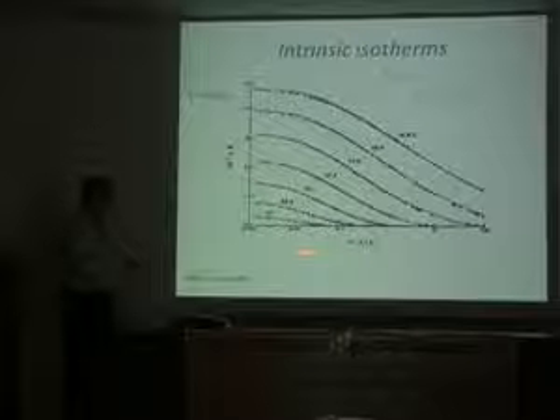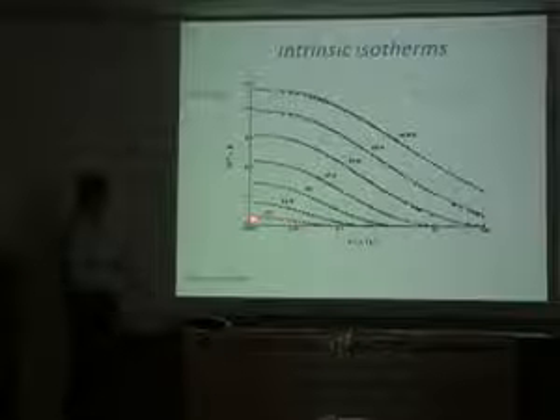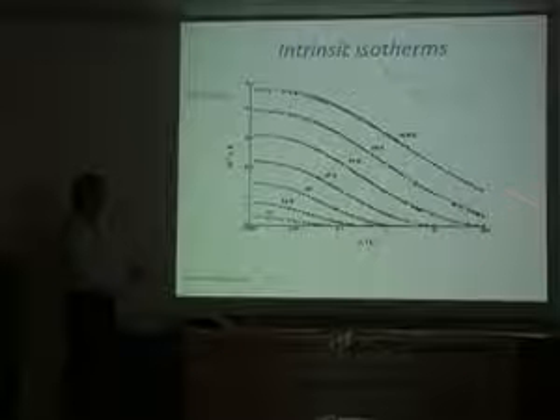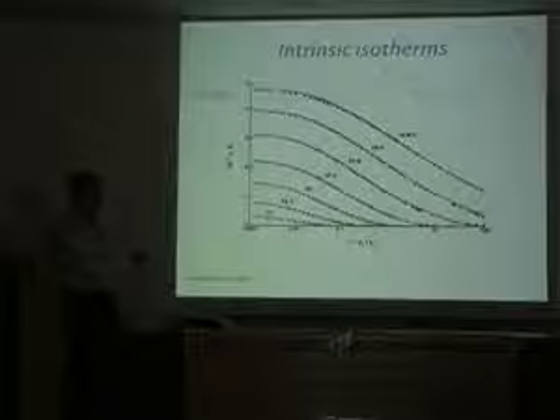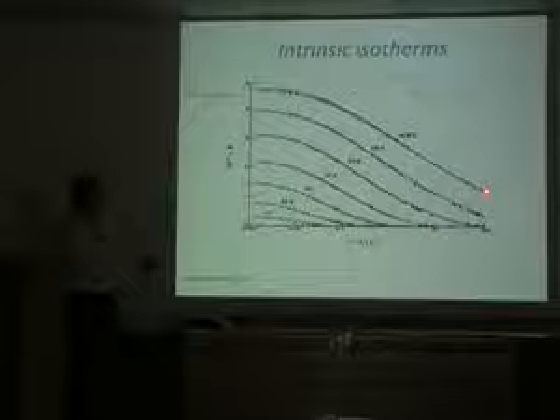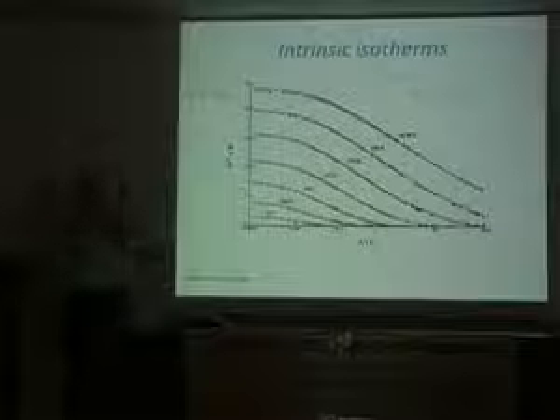So what Kovacs found was that the volume, and this could be enthalpy, it's just a departure from equilibrium, as a function of the time after the quench, looks like this. He quenched from 40 degrees to, here's 35 degrees, as the material ages or comes towards equilibrium. It's pretty quick. As I go down in temperature, these times get longer and longer. By the time I'm 20 degrees below the nominal glass transition, the time to get into equilibrium is, well, this is 100 hours, so it's now getting very long. And if I go down another 5 degrees, it's going to get longer and longer. This is the story of the geological age, right? These things are just going out to longer and longer and longer times.